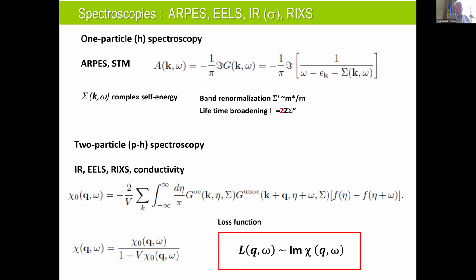And then you have a convolution of two Lorentzians. So you would expect that maybe the scattering rates in the two-particle spectroscopy would be just twice the scattering rate in the one-particle spectroscopy. And when you then calculate the susceptibility, you can do RPA, and from this you can calculate the loss function, which is the imaginary part of the susceptibility.